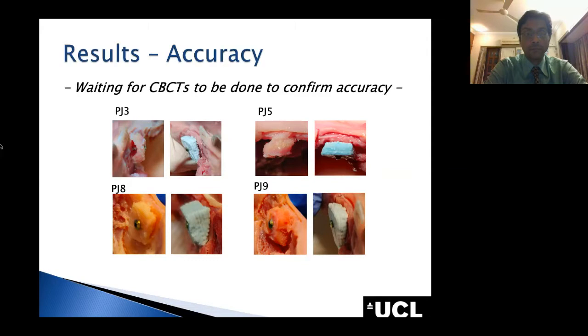In this hole, normally, I guess the surgical team would insert this powder that Federico showed before, which could be hydroxyapatite powder or any other type of powder to fill the gap. And you can see that on the other side, the 3D printed implant is really matching all this. Similarly for pig jaw number 5, 8, and 9. But we still need to wait for quantification of this accuracy from the CBCT, which will come soon, hopefully.